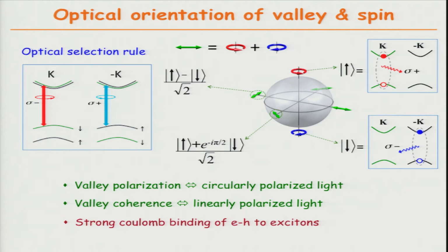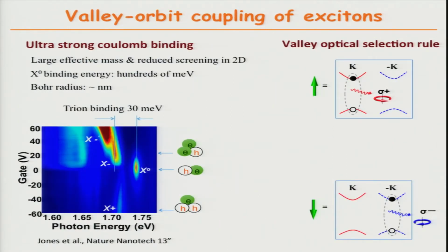So in this system, excitons also have interesting properties because of this strong binding. You can either have the neutral electron-hole pair or charged electron-hole pair when they capture an additional hole or electron. And for this hydrogen-like bound state, in this material, it has a binding energy that is more than one order of magnitude stronger than in gallium arsenide, and the Bohr radius is really small. That means electron and the hole have a much larger opportunity to get on top of each other, which leads